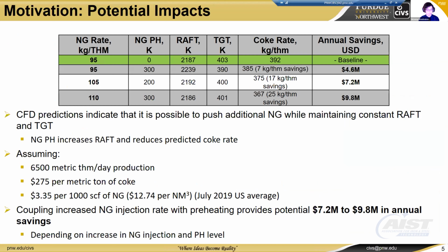So current CFD predictions indicate that it's possible to push additional natural gas while maintaining constant raft and top gas temperatures. The natural gas preheat will increase the raft, and it also reduces the predicted coke rate. This right here is our baseline case with no natural gas preheat and our standard natural gas injection rate. If you combine increasing the natural gas injection rate with preheat, you can see we can keep nearly identical raft and top gas temperatures with a lower coke rate per ton of hot metal, resulting in $9.8 million in annual savings.